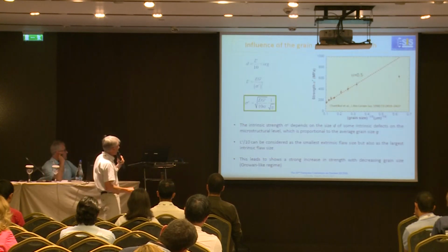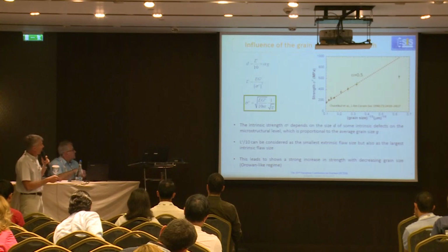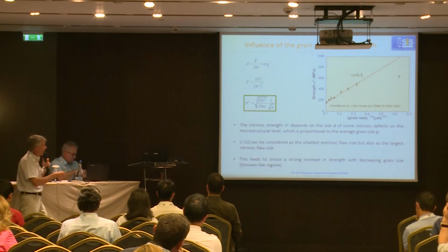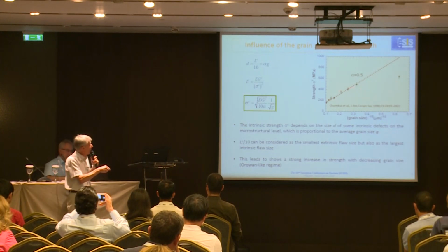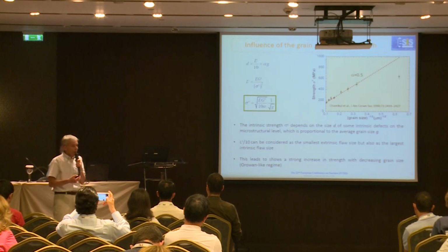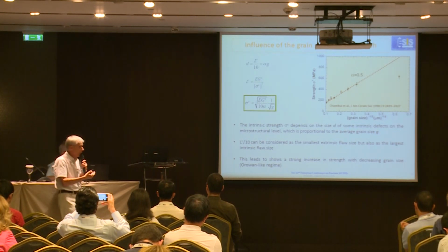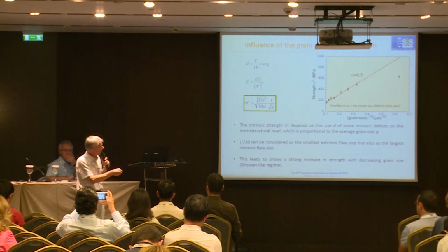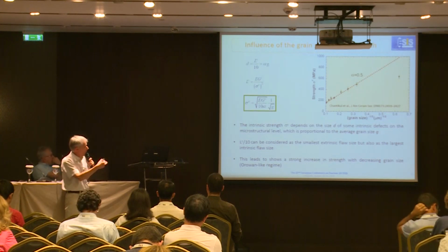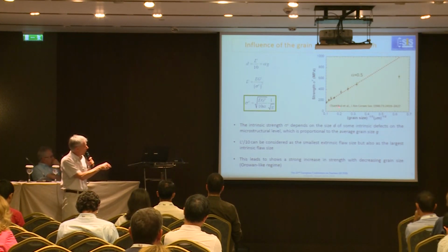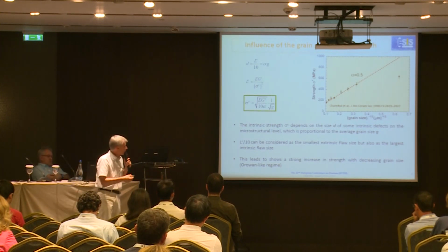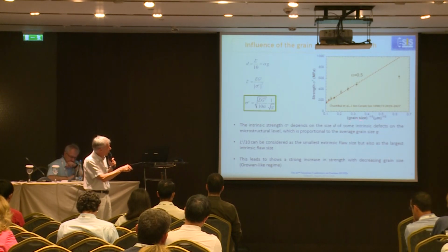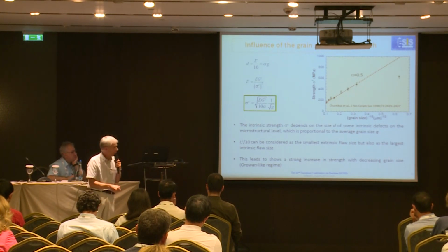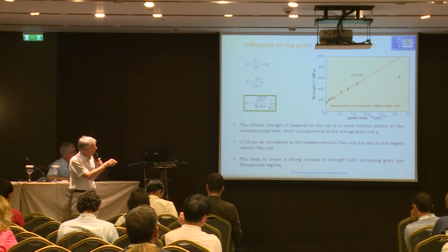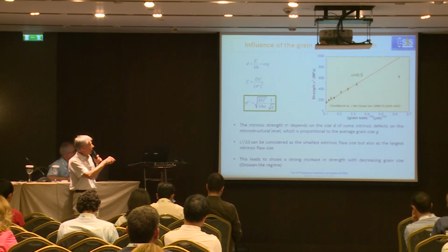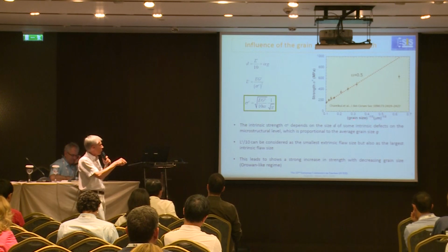Okay, just one last slide. It is well known that the strength of ceramic materials depends on the size of the microstructure. If you decrease the grain size of ceramic materials, you will increase the strength. This is plotted here. This is a standard plot for ceramic materials. I use the data of Chantikul on alumina. The strength is plotted versus the inverse square root of the grain size. And you obtain a line here, which shows that the strength is proportional to the inverse square root of the grain size.